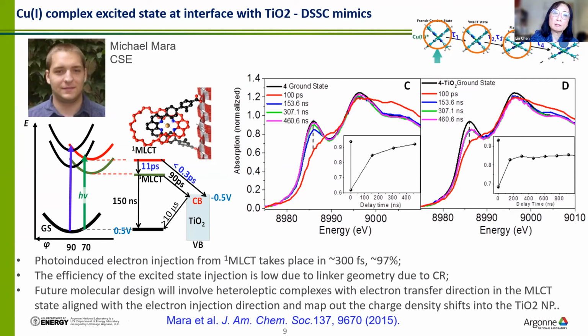It matches the optical study in the solution, about 150 nanoseconds. However, when it's connected to, bound to the TiO2, notice there's two different time scales. So this is up to the microsecond, still flat. So that's the injection into the TiO2, and that's sustainable at least about 30–40%, but the remaining probably recombine at the surface.